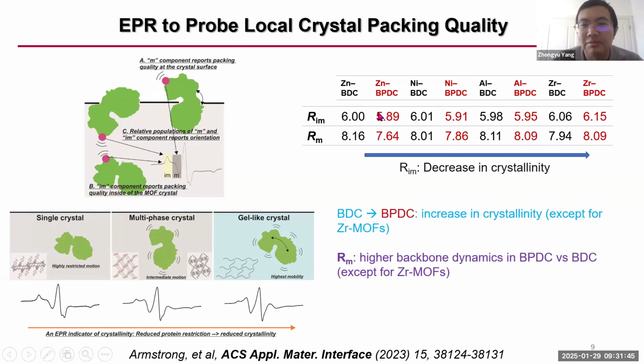Now, comparing BDC to BPDC, you can see even though the length of BPDC is longer than BDC, we actually see an increase in crystallization, therefore a reduction in rate. That means even though the linker is longer, you can form better crystals. I said except for the zirconium, the gel, because when you form a gel, the longer the linker, the bigger the gap, and the higher the rate, right? So basically, we use the EPR fitting parameter. We figured out a rough way to correlate the crystal packing quality with the rate parameter of EPR.